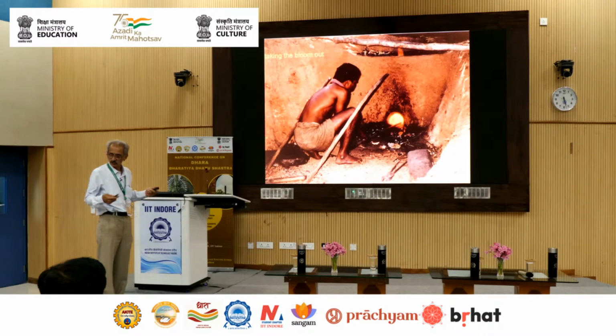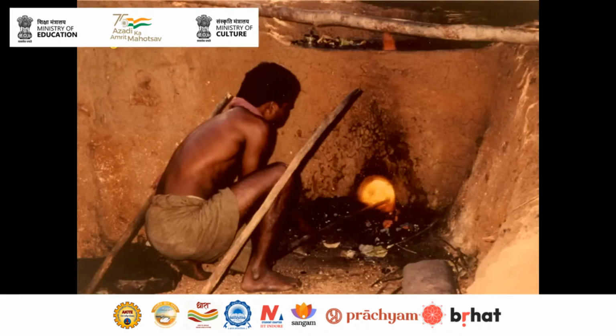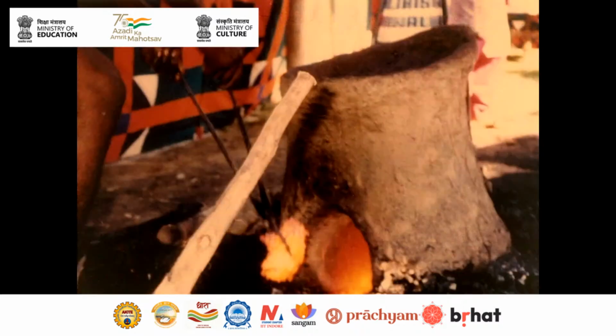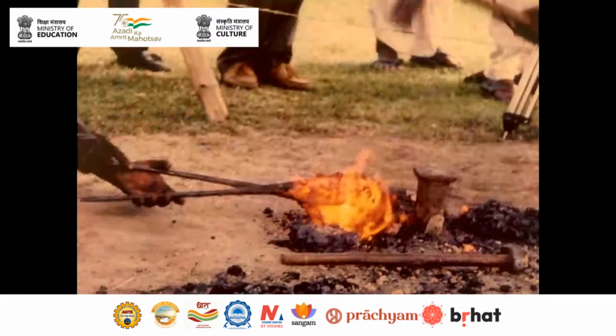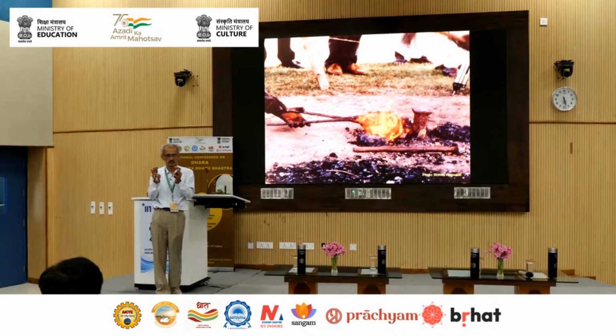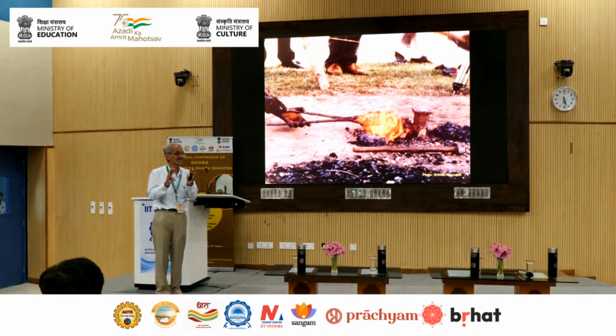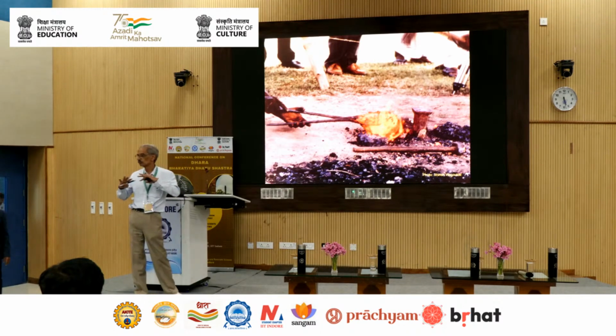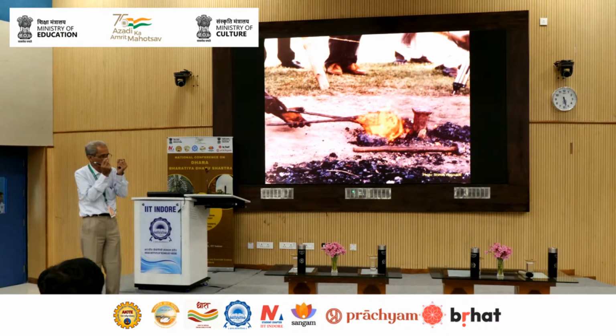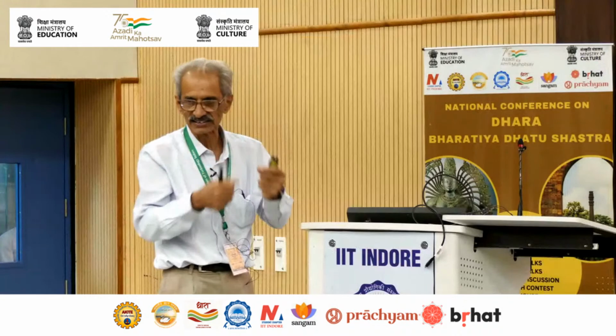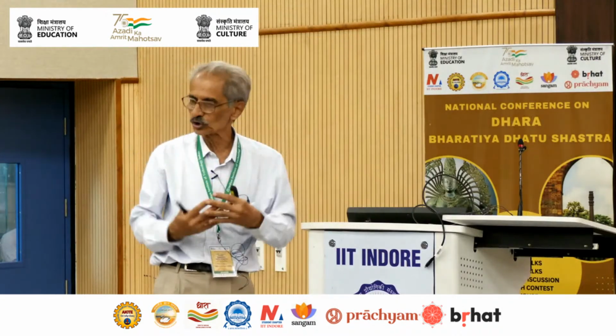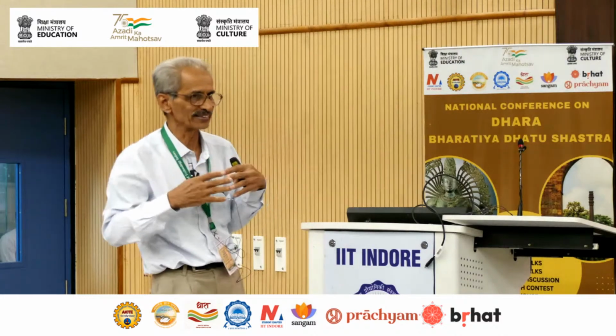So at the end of this operation for around 5 hours, you break this wall. That opening is closed with a temporary wall. It's broken here, for example, and then he will take out the bloom, and then the bloom has to be immediately forged, because the good thing in this operation is that when it's taken out, iron is solid, so you have the bloom, but the gangue is liquid. So that as soon as you take it out, because the iron otherwise are all granules, it's like the DRI. So as soon as it comes out, you have to squeeze out the slag. So that's why the temperature is very crucial.